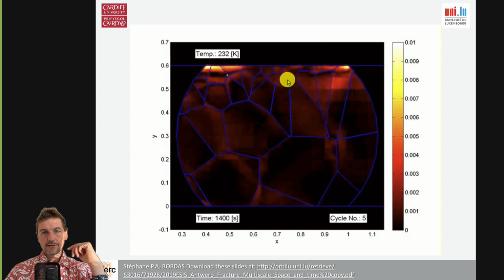So in that case, we have a model where cracks initiate along the interfaces. We compute the damage around the interfaces, and when the damage, due to mechanical thermal fatigue, increases beyond a threshold, we crack the whole grain boundary. Then we look at the propagation of the cracks, and at some point a crack will grow, and all the small cracks will coalesce, and the whole solder joint will fail.